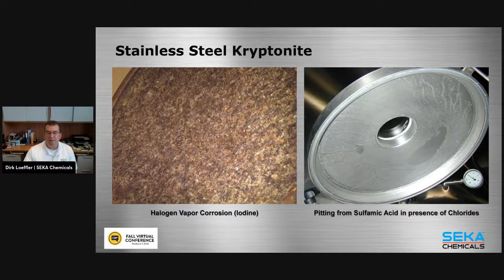We do find that pitting from chlorides is a lot more pronounced in acidic environments. So even lower amounts of chlorides in a highly acidic environment can produce pitting and halogen corrosion. This here, for example, is a brewery in the Northeast, where we have elevated chloride levels in the water. The brewery was using sulfamic acid on their brew house, but did not take the chlorides out of their water and ended up with chloride pitting on the manway cover from their brew kettle.